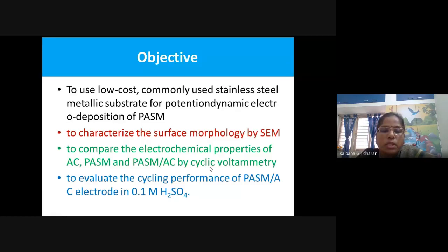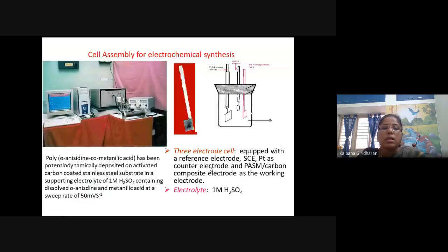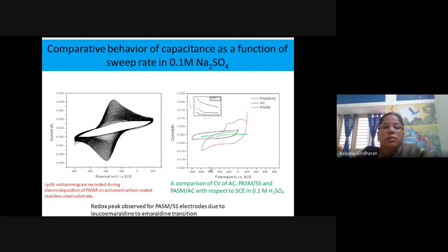To compare with plain activated carbon, we initially took stainless steel, applied activated carbon over it, and then electrochemically deposited polyaniline on it, to evaluate the cyclic performance with 0.1 molar sulfuric acid. So this is the technique we have used.